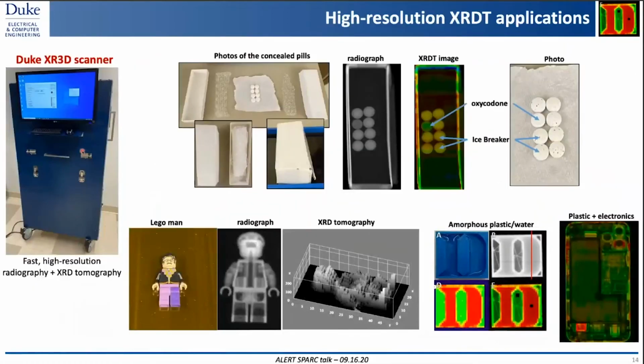We've also built another system at Duke, what we're calling our XR3D scanner, which is currently in the Duke pathology lab in the Duke hospital. It was built to be able to take data for medical sample analysis, and it's limited to thinner samples, but it's a very high spatial resolution system. And so we've played around with this same drug detection challenge where Stefan placed some oxycodone hidden next to some icebreaker gum and placed it inside of some bubble wrap, inside of a box, and put it in our scanner.